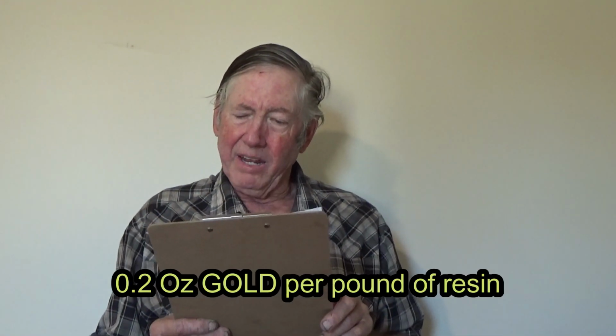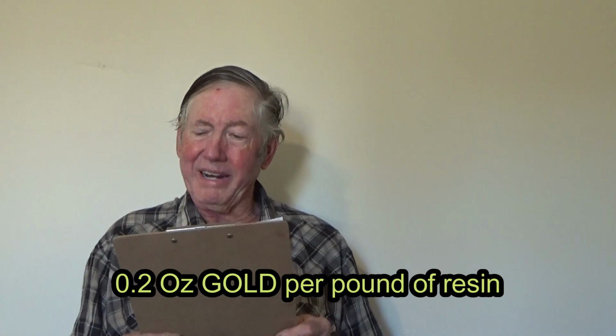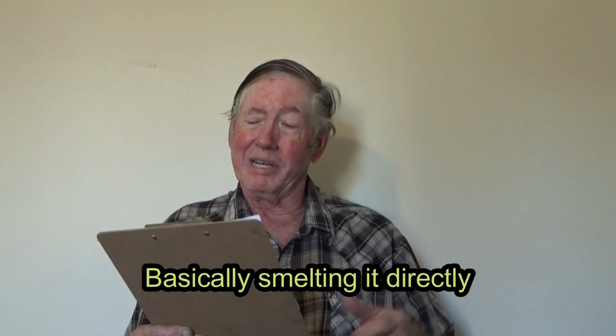And AR3 was 2.66 parts per million, which was 91% recovery. So clearly AR3 was the winner. And it loaded in this test to about 0.2 ounces per pound of resin, or about $350 per pound in the resin. Now this resin only costs $20 to $25 per pound, so we can easily ash it at that and still make money. But I'd like to see what exactly the maximum feasible loading is, because we might be able to run it several times that.